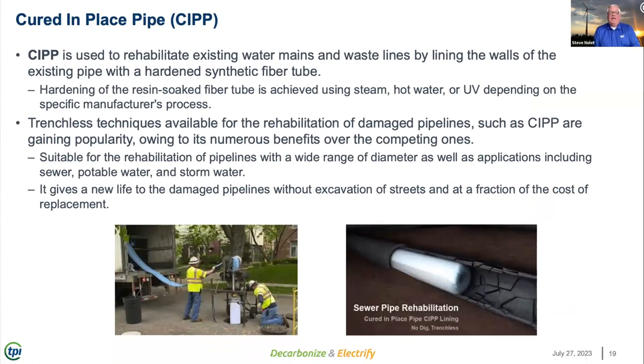Let's talk about a simple example. I think maybe one of those kinds of examples that could consume a great deal of reclaimed fiber. You may be familiar with cured-in-place pipe for rehabilitating our infrastructure. Primarily, CIPP is, it's not a new process. It's been around since at least the mid to early 1980s. It's a process in which we can reline our infrastructure, mostly waste lines or water mains, with a liner that's composed of polyester felt that's saturated with a reactive resin. It's blown into an existing pipeline, expanded against the wall of the pipeline, and cured in place. And that pipeline is put back online without digging up the streets. Cool idea.